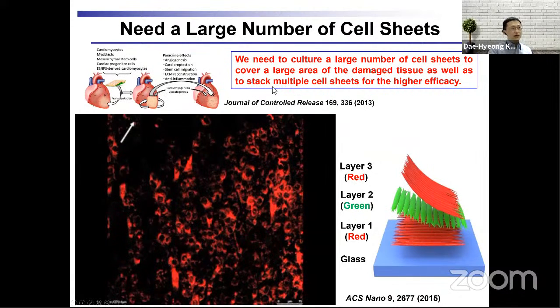In addition, if we stack multiple cell sheets, the therapeutic efficacy usually increases. So typically we stack 5 or 10 layers of cell sheet. That means we need to transfer print multiple layers of cell sheet. Actually, that initiated the development of the new transfer printing method, because it is quite challenging to change the temperature between body temperature and low temperature several times. Rather, this transfer printing process is much easier. But anyway, that means we need to develop a method to culture cell sheets in large quantity.